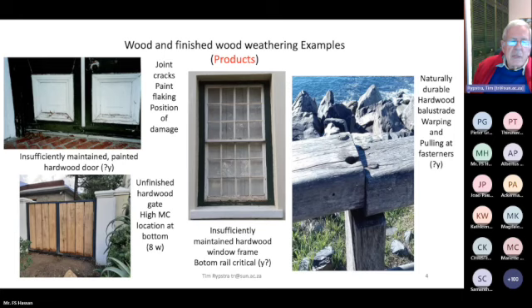you see these lines which accentuate the joint. And as soon as these become visible, then you know there is excessive moisture coming in at that particular point, and also excessive moisture which accumulates at the bottom rail of these fielded panels. Similarly with the window in the center, at the bottom you will find that the bottom parts of products, because of gravity, are always suffering more than others. Water runs down and accumulates, especially if there's the possibility of water accumulating at the bottom. That's where at the corners, at the joints, you will find the water seepage through the coating, and then the whole deterioration or weathering. It's actually called weathering, but it is part of fungal degradation as well.